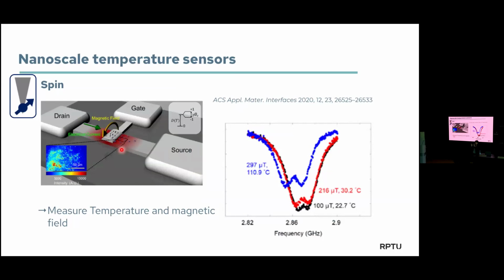And when you are changing the distance of the atoms around your color center, of course, you're changing the electronic wave functions at your color center. And what people find out is when you're changing the temperature, you're not splitting the resonances, but you're shifting the two resonances together with each other. And this, the group here has used to correlate two things, the magnetic field and the temperature.